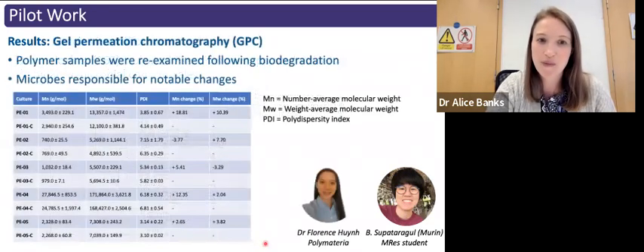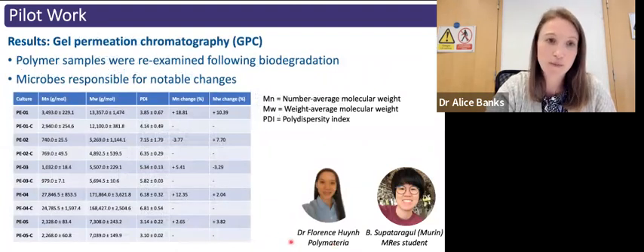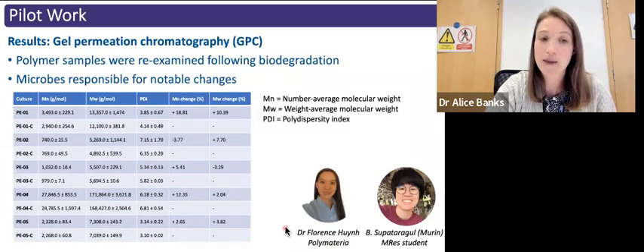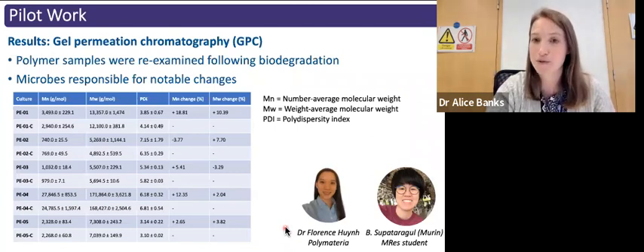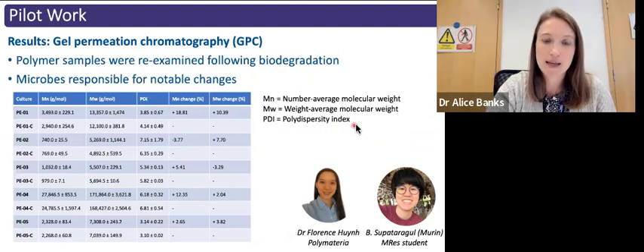And as well as looking at the microbes themselves, Murin, in collaboration with Florence, based at Polymateria, went back and recovered the plastic particles, and these were examined using a process called gel permeation chromatography. And this allows us to examine the molecular weight and the relative size of the population of plastic particles remaining. So these were examined by looking at the number average and weight average molecular weights, which leads to this polydispersity index, which is the metric that we're particularly interested in.